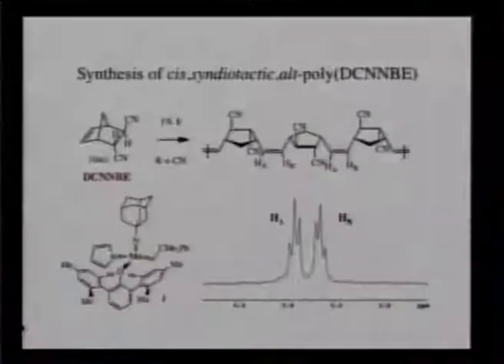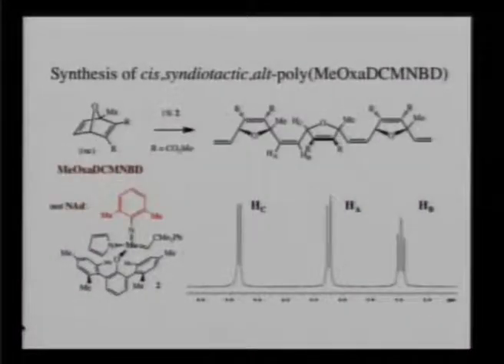These are, in fact, the two olefinic protons in that all-cis polymer. They're different, and they're on the same double bond, so they couple with one another. This is a little bit of trans product, so it's not 100% pure. It's greater than 95% one structure. You can do that for the cyano version, same sort of story. And you can do it also for other kinds of monomers, such as this one, this methyl substituted oxanorbornadiene. You get an alternating enantiomer polymer.